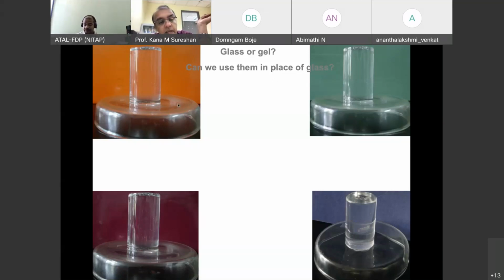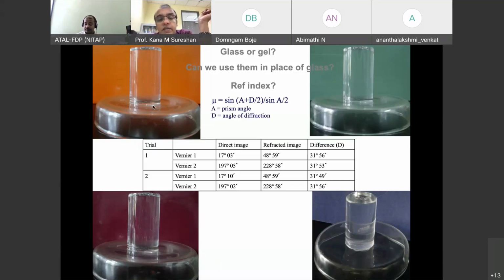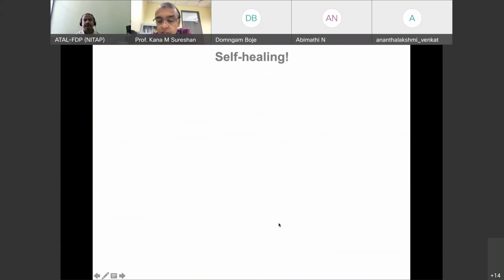Now we have a gelator which can make a transparent gel in different oils, and this can possibly be a glass substitute. We have checked the refractive index of this material and we found that it is 1.46, which is nothing but 1.5. So we have a glass like gel. Can we substitute glass? That is the question next.